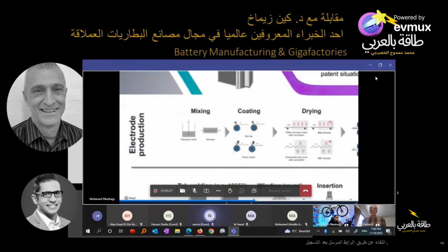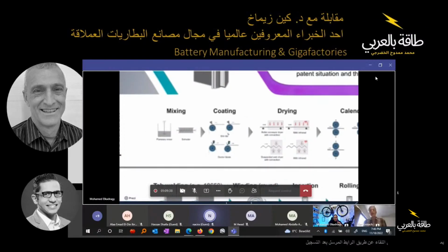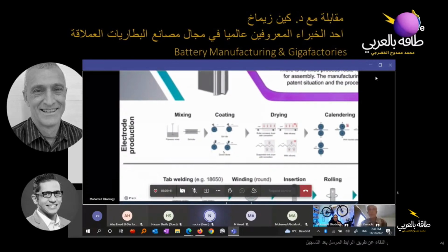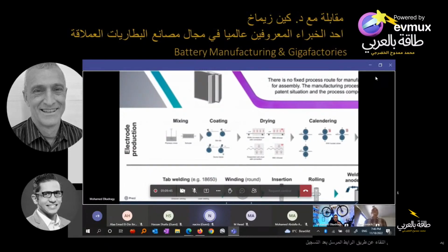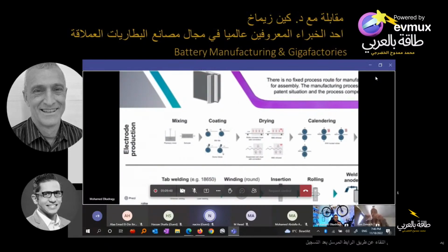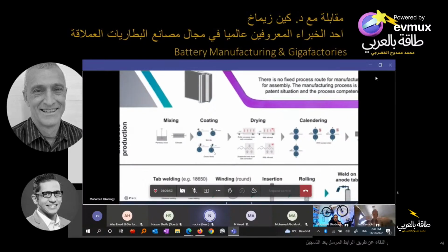You've made your slurries. They've got their glue. They're this mixed up goo. Now you're going to coat onto your foil. Anode starts with A, coats onto copper. Cathode starts with C, coats onto aluminum. And what happens is there's many different coating techniques, but think of, you almost, extrude is the wrong word, but you have these slot dies usually, and you pump this fluid out and dispense it while the foil is going through this long system. And that long system takes the bare foil, wraps it up through, gets coated with a thin layer, and then that gets run through drying ovens, because you need to now get rid of the solvent now that you've coated it.